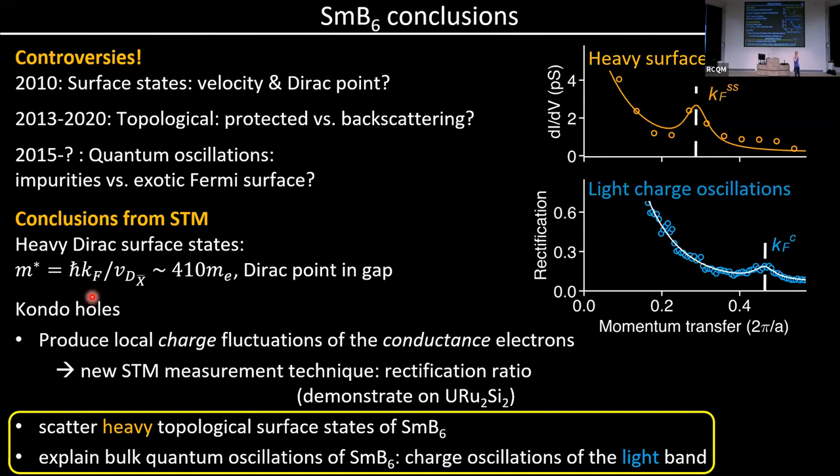Well, I guess it does. In our model, there's a big fudge parameter, which is what fraction of the surface is what termination. So we're essentially averaging two terminations. And we threw in 50% because we haven't imaged a big enough area ourselves to really have good statistics on that. So I think that if you had a 3+ surface and a neutral surface, the result of our model would not be any different than just changing the fraction of one surface versus another. We were able to get a pretty good quantitative match with a 50-50, but in reality, you're right, maybe some surface had more charge, but there was less of it.